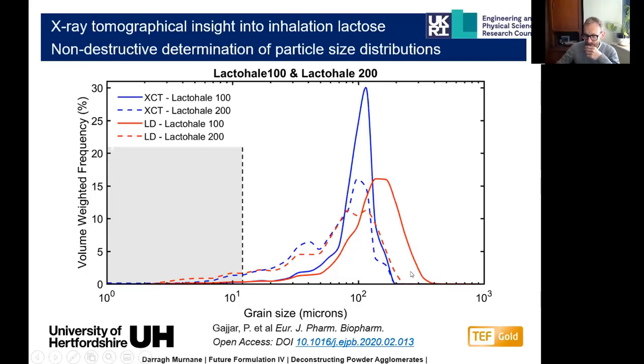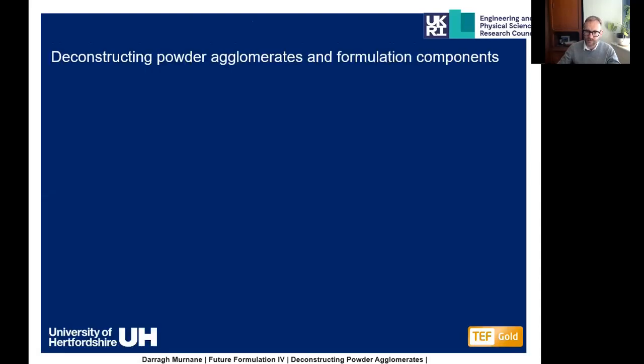So many of the particle size techniques that have been available to date show a preferred orientation of the particles as they move through lasers or as they settle onto microscope plates. And the XCT approach images that powder as it's present in the bulk material, and we're able to pull out particle size distributions of that powder as it appears within the capsule. And this removes a lot of the artifact of the typical particle size distribution techniques.